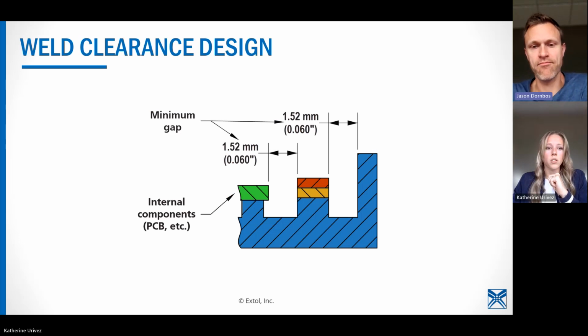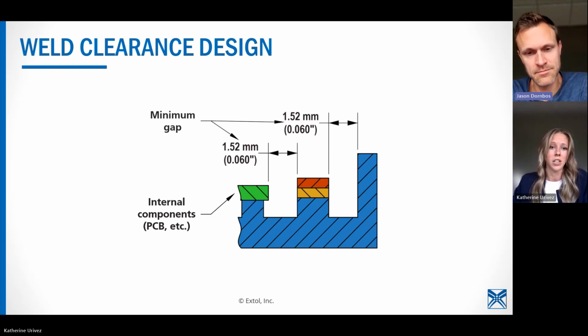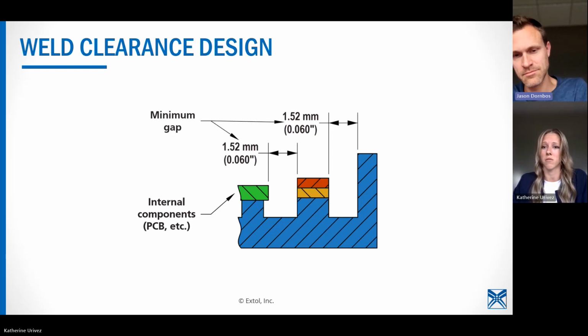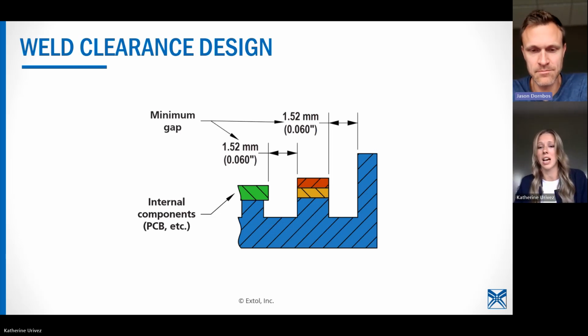And then weld clearance. So say you've got that internal component like a battery, or you have a skirt on the exterior to prevent that ugly flash from showing. That's totally doable. You just need to have clearance for your heated tool. So your heated tool needs to have about 1.52 millimeters of clearance from those features. Again, this is a minimum.